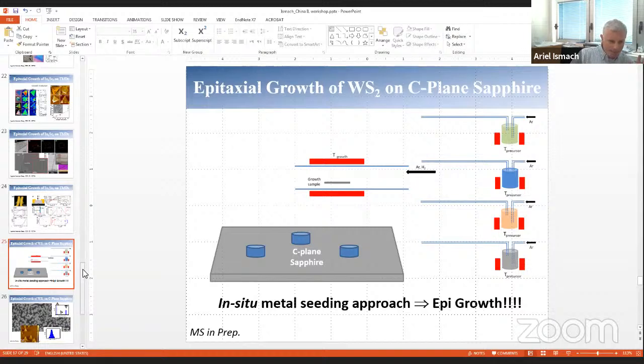And with regards to the growth of TMDs by such van der Waals epitaxy, it was shown by a few reports that by the same or similar methodologies that I showed you before, these TMDs can grow epitaxially on, for example, C-plane sapphire. And from our experience, we noticed that you can get epitaxial growth or you cannot get epitaxial growth.